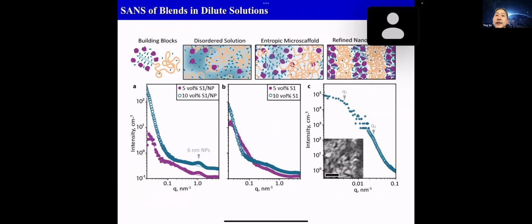And then we just have to identify at what concentration the system is going to form what. So in dilute solution, it is quite important to map out where the individual components are. And again, the entropic driven phase behavior is highly valuable, because if you have this repulsive enthalpic driven assembly, you're going to have trouble even getting the nanostructure assembled or even getting the molecules together, because the solvent completely shields off repulsive interaction.